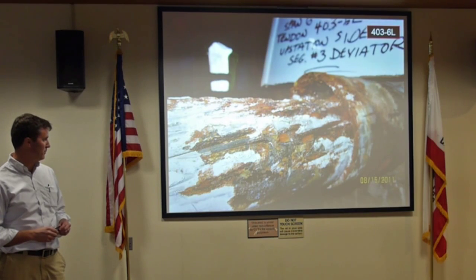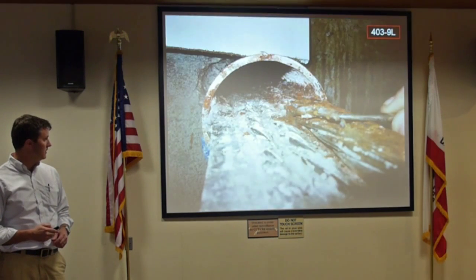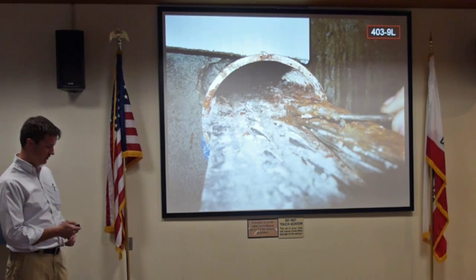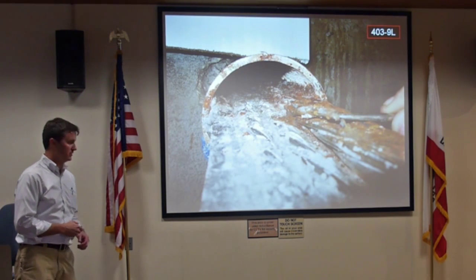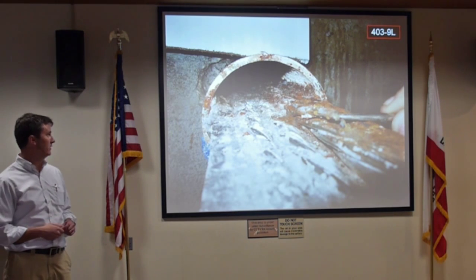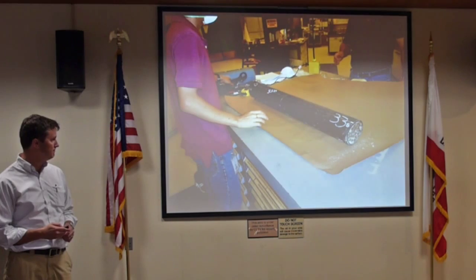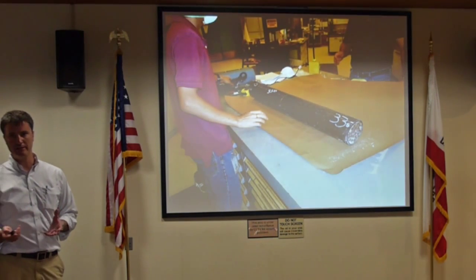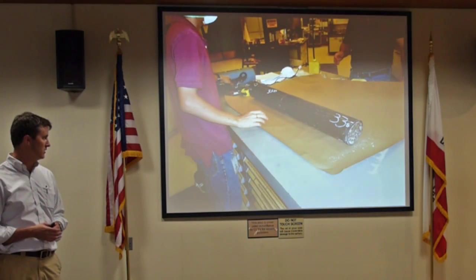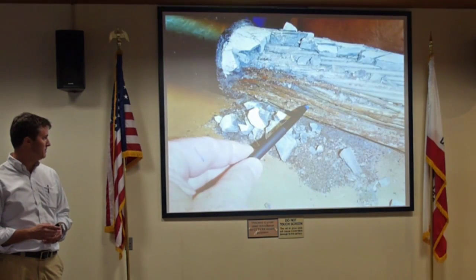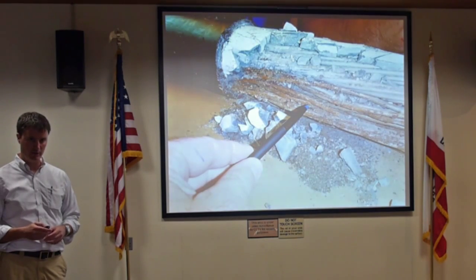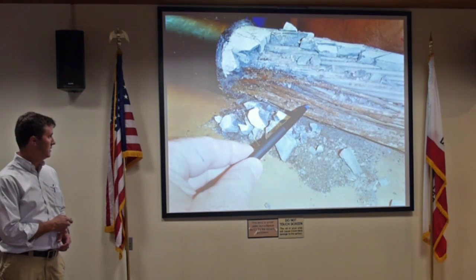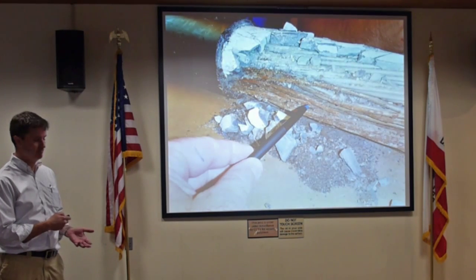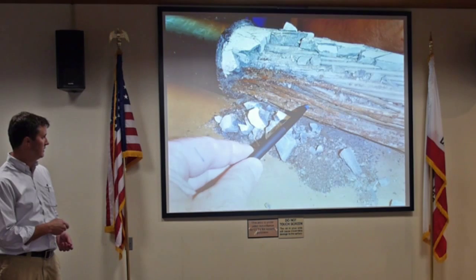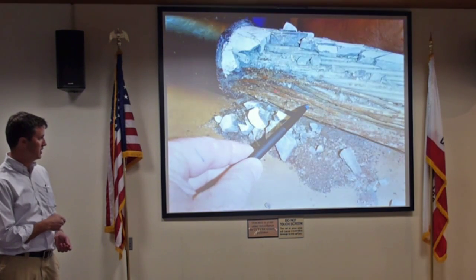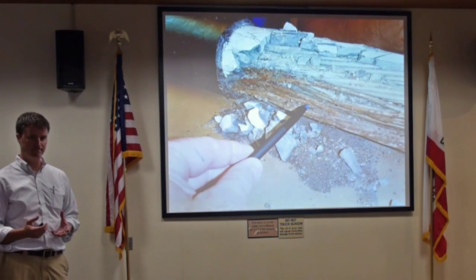So they found pretty severe corrosion. And in addition, this is actually supposed to be entirely filled with grout. You can see a significant void here. This is at the high points of this external tendon. So they took some of the failed tendons, because they wanted to look at some of the residual materials, the strand as well as the grout, and took it back to the laboratory. And the interesting thing is that it seemed to be kind of a localized phenomenon. You can see on the top side the strand is in good condition, but on the underside of the tendon, you can see there's a wire break right there. You see the strands are corroded. And so there's something going on at a localized level.